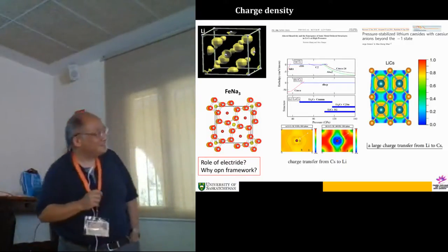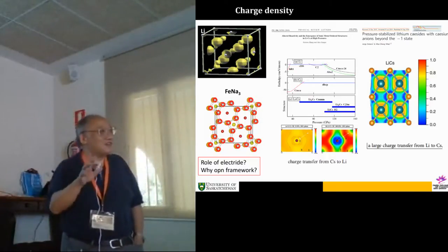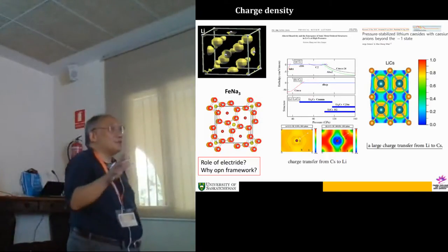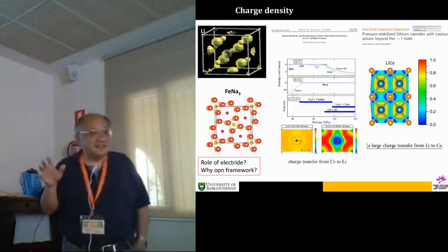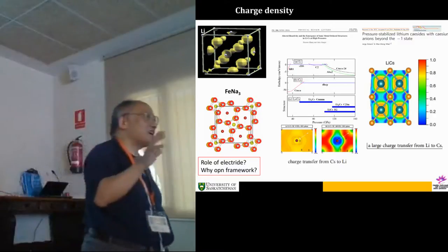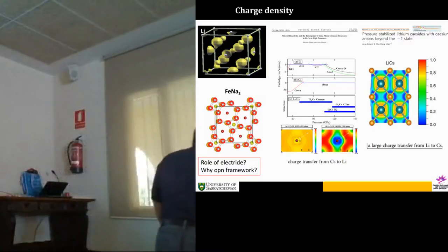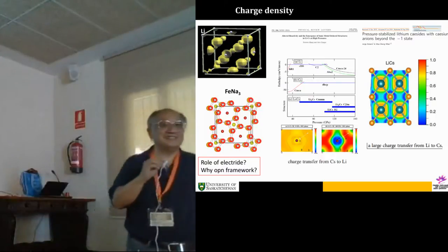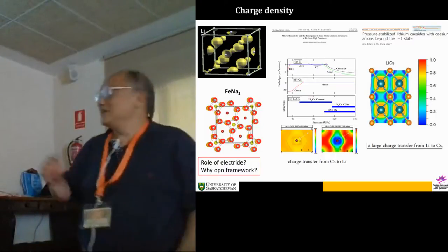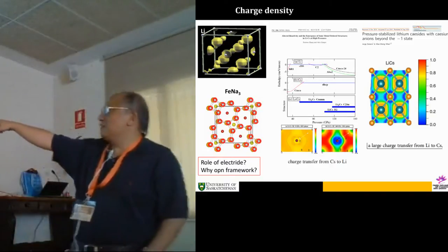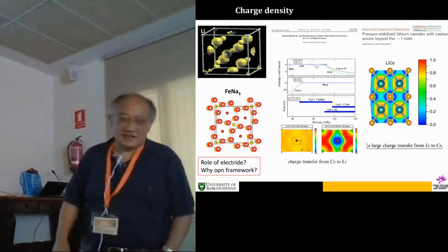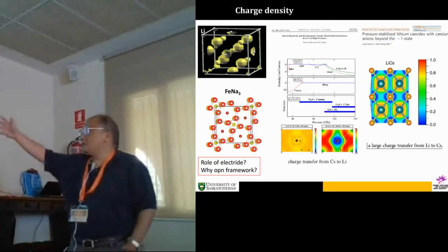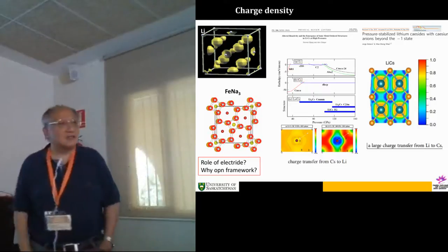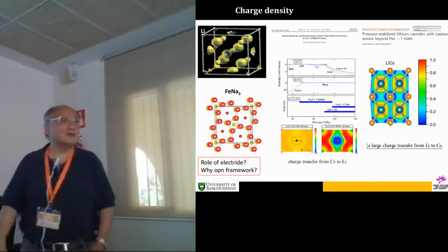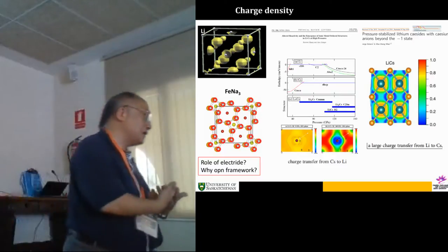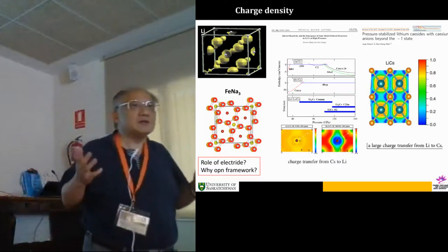So that's a question. At high pressure, you use the conventional one. If you use uranium, it's no problem because you have 92 electrons. It's totally dominated by the core. It doesn't change much. Your scattering factor is good. But if you have a light element, first row, what do you do? That's a question. All right? And you often see very funny structures, like carbide structures with electrides. This is, again, a prediction for iron sodium 3. They sit in the middle. So what's the role of the electride? Why is it there, and why do you have an open framework? You would expect that the more you compress, the more dense-packed the structure gets. Why do you have open structures?